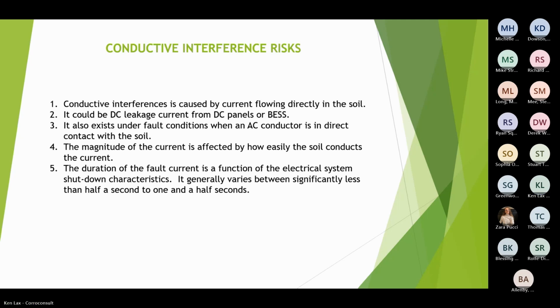Now, from the pipeline point of view, this conductive interference doesn't directly and immediately affect the corrosion risk. And it's wrong to think that these very high voltages will blow the coatings off. That seldom happens, and not under these kind of fault conditions. What it can do is change the characteristics of the coating.